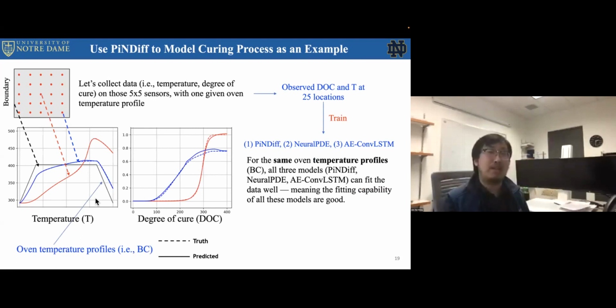Once we train these models, the model can predict the temperature and degree of cure evolution over time for anywhere in the sample. Here I'm just showing you the temperature evolution, the temperature time sequence at the center, and this blue one is the temperature at the corner. The blue solid curve is the oven temperature profile over time, so it's more like a boundary condition. And this one is for degree of cure.